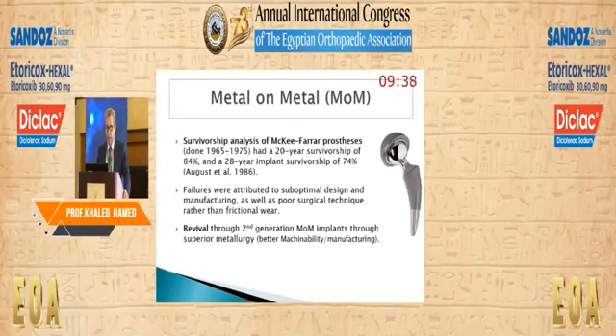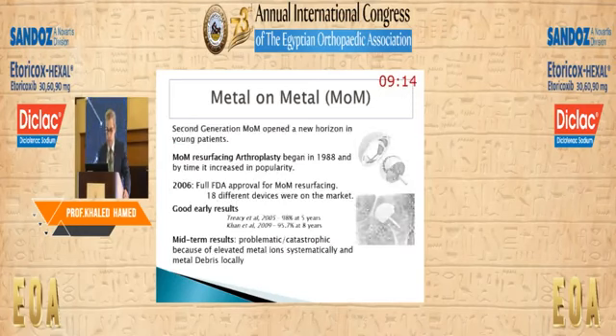Back to metal on metal, we have seen that we started actually in total hip replacement with metal on metal prosthesis, and several years later, the survivorship of the early McKee-Farrar prosthesis led to a revival of metal on metal arthroplasty. And it had been shown that the problem was in the machinability and not in the frictional wear, so that in the year 2000 we had a revival of second generation metal on metal arthroplasty. And by the year 2006, there were 18 different models. They offered a good early result, but the midterm results were problematic because of the systemic and local metal debris.